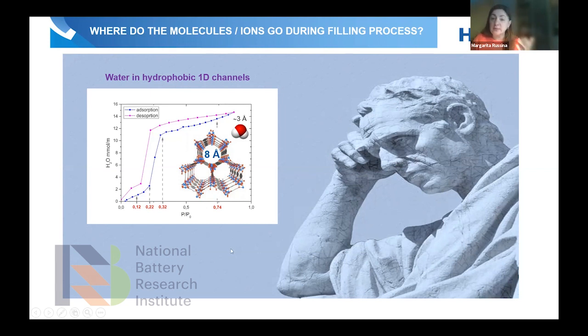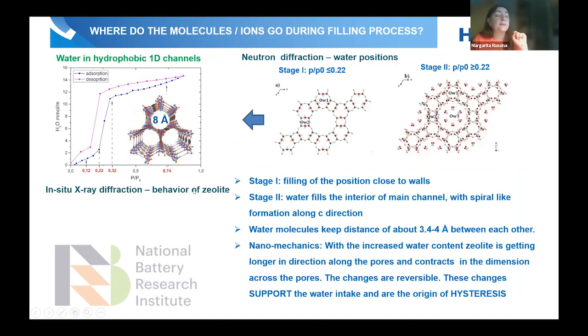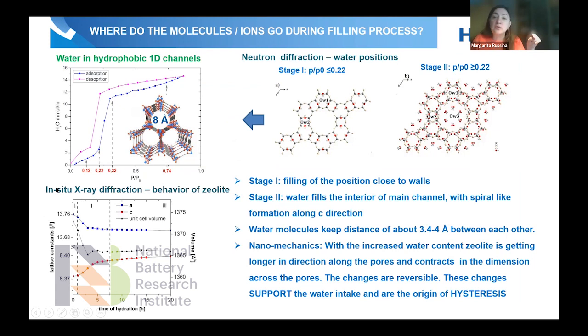So this is a relatively simple system, and we wanted to know how water fills these places. We applied neutron diffraction to investigate where the water is, and also X-ray diffraction to see whether we see changes in the framework itself. Originally, this system is described as a hydrophobic system, so we do not see really a chemical bond formation between the water and the zeolite. However, we still do see quite some interactions in there. So first, what we have found out by application of diffraction, there are basically two stages of this filling process. In this first stage,